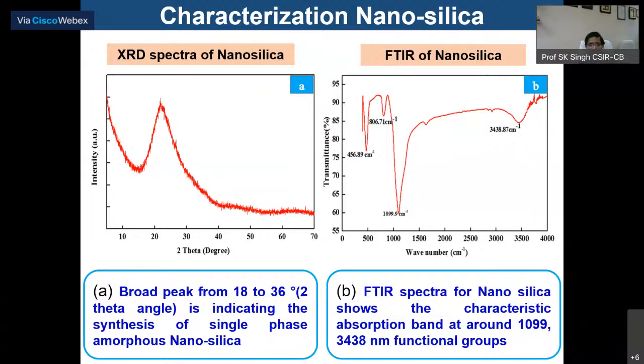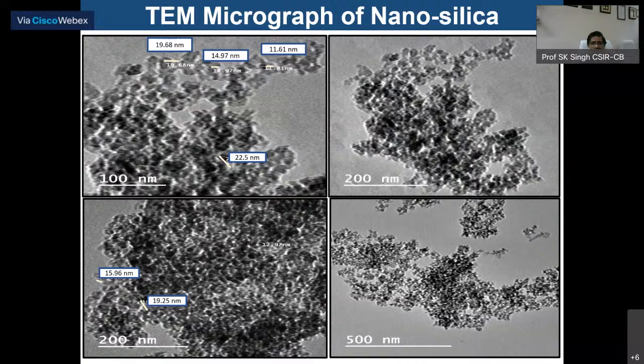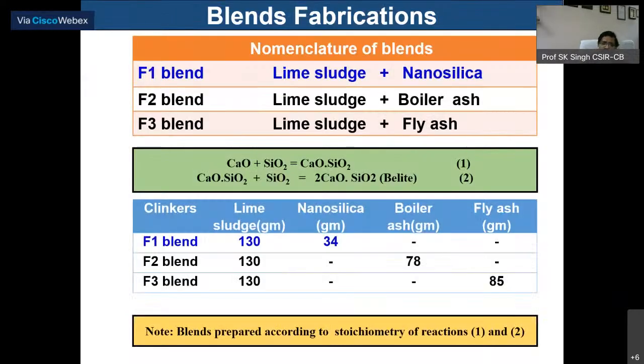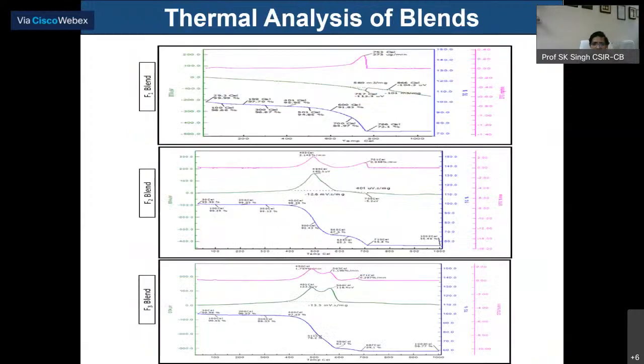If you look at the XRD, it is amorphous because haziness is coming in all those 2 theta values, and it is mainly a single-phase amorphous nanosilica, also with the FTIR analysis. So if you look into that, all those microsilicas are being separated, and we can use them there itself at paper industries to make better, strong bricks and blocks with high strength. And we have carried out work with different blends, and we found that with our F1 blend, where lime sludge for small cubes is about 20%, we can achieve a good concrete system.